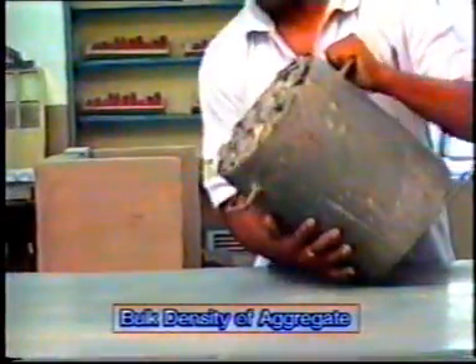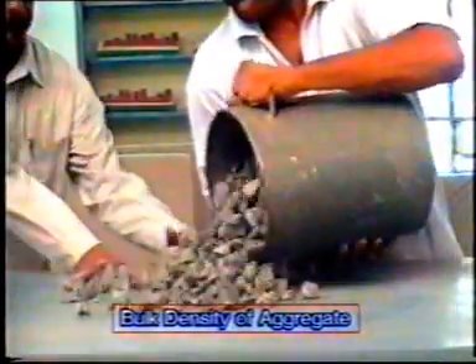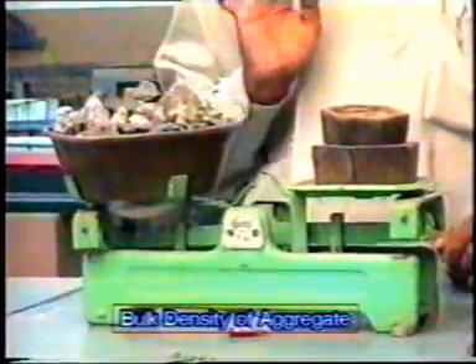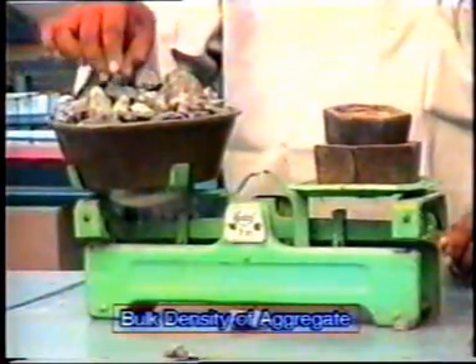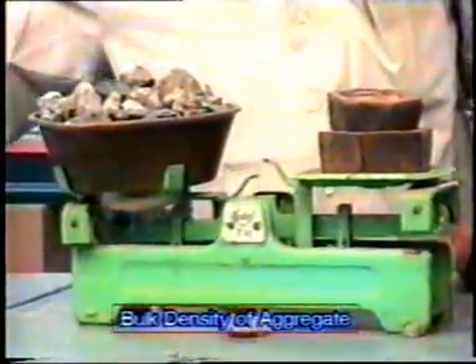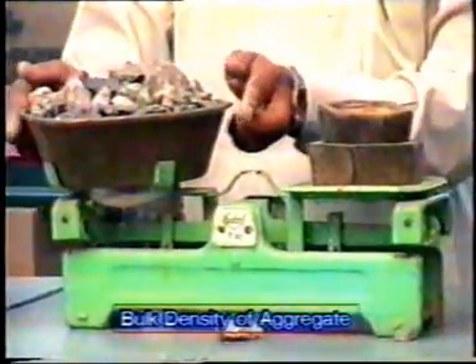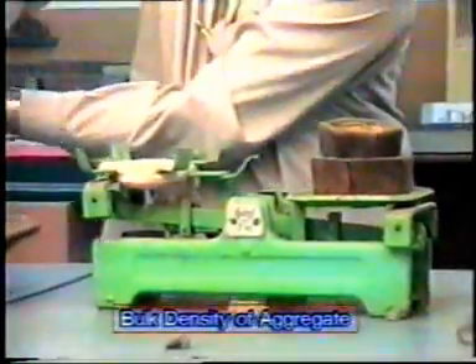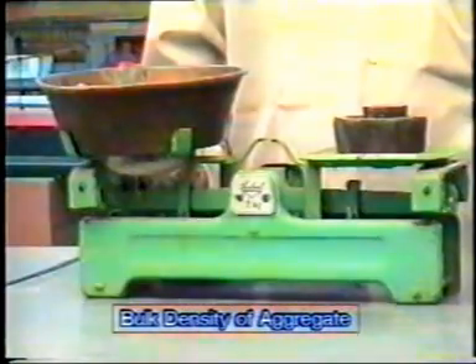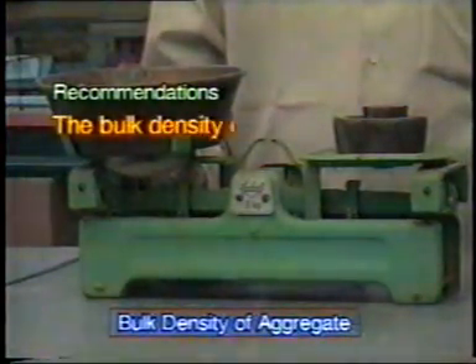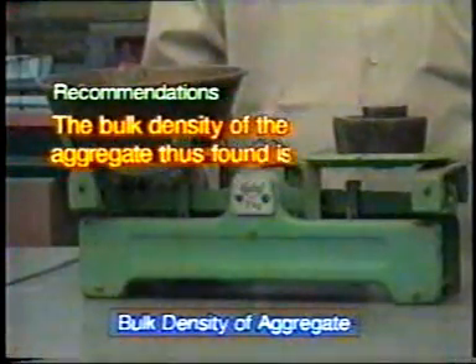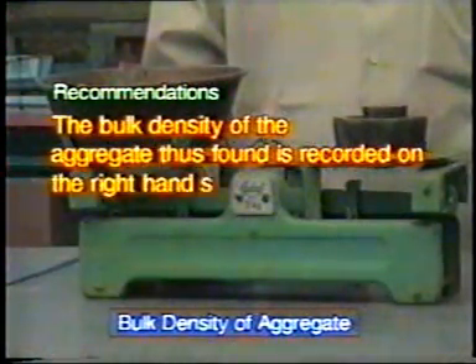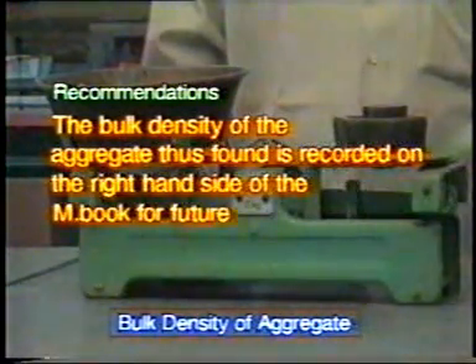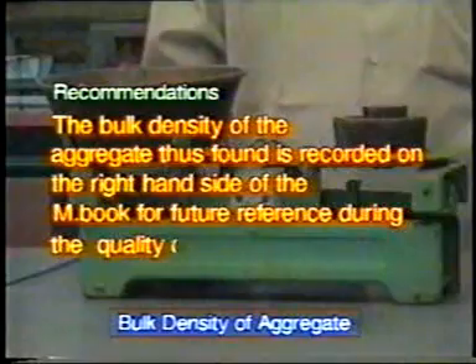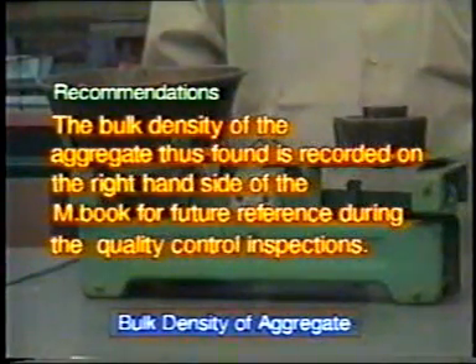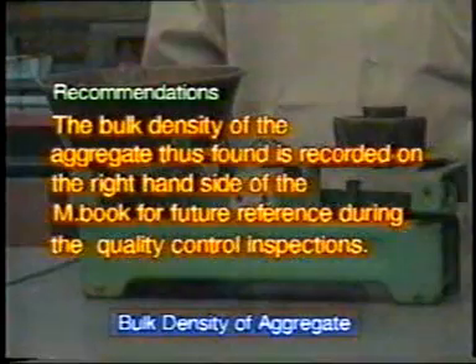Now weigh the sample of the aggregate filled in the measure and report the bulk density of aggregate as the weight of sample of aggregates in the measure divided by its volume. Recommendations. The value of bulk density of aggregate thus found may be recorded on the right hand side of the M-book for future reference during the quality control inspections and inspection by other higher officers.